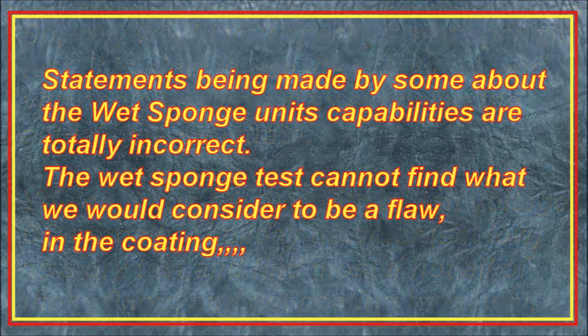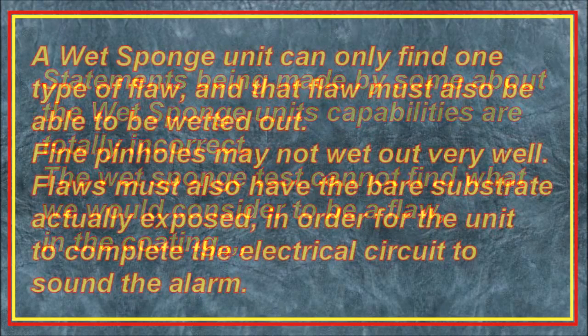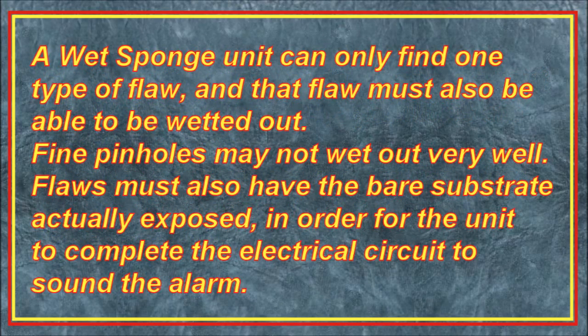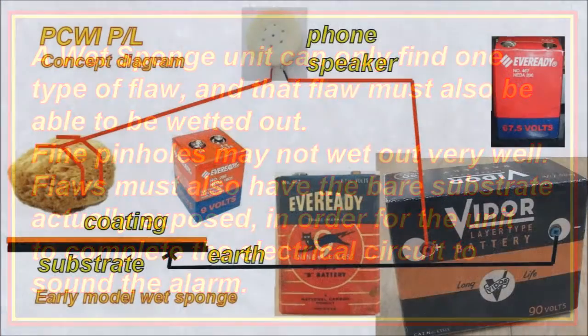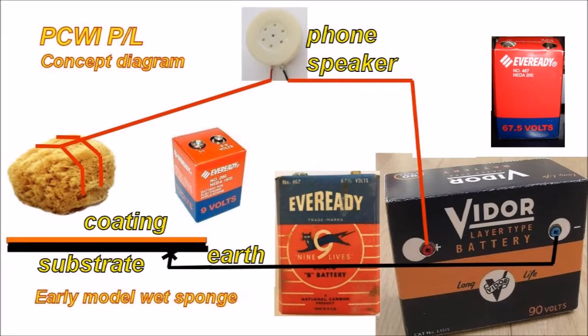Statements being made by some about the wet sponge unit's capabilities are totally incorrect. The wet sponge test cannot find what we would consider to be a flaw in the coating. A wet sponge unit can only find one type of flaw, and that flaw must also be able to be wetted out. Fine pinholes may not wet out very well. Flaws must also have the bare substrate actually exposed in order for this unit to complete the electrical circuit to sound the alarm.